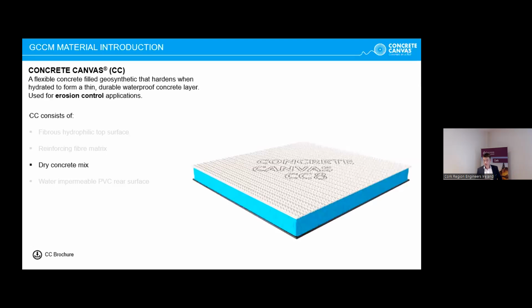So an important component. The third element is the actual dry cementitious powder mix itself, which has a very high early strength gain. It gains 60% strength within 24 hours, and it has a 28-day compressive strength of 60 MPa for the middle thickness, or Type 2 material. Finally, on the bottom, we have a PVC rear face, which is your geosynthetic component, and everything in the GCCM, the concrete cementitious component, is designed to protect this from any damage in the field. So that is your back component that should be protected from your overlying concrete material.